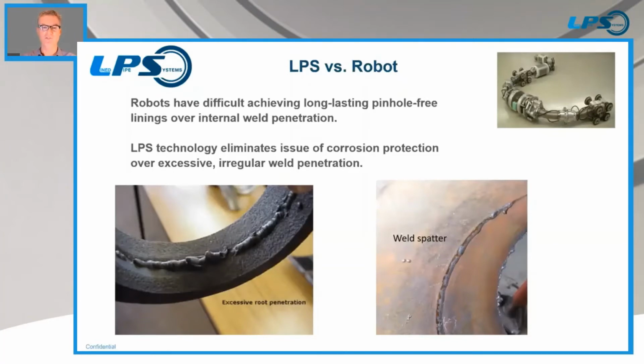So you've got a few photos here showing some jagged weld penetration. I'm sure it's not always that bad. You've got some weld spatter. So any of those locations are going to be very difficult to get pinhole free. And even if you do get them pinhole free, it might be a pinhole location that would open up in the future. Our technology completely eliminates that issue. Our rings actually make welding easier and reduce the frequency of weld defects because they serve as backing rings.